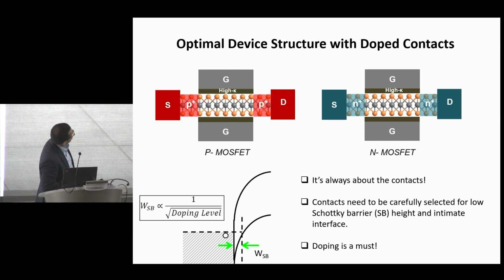I think the optimal device structure perhaps will be what is shown here and here, where you have a dual gate, you have the contacts, whatever material you use, whatever metal you use, maybe they're raised contacts as well, but then you have these heavily doped extensions. So this is very much like how we make our conventional MOSFETs. You need these heavily doped extensions to reduce your contact resistance. This is how we have been classically overcoming the contact resistance problem in silicon.